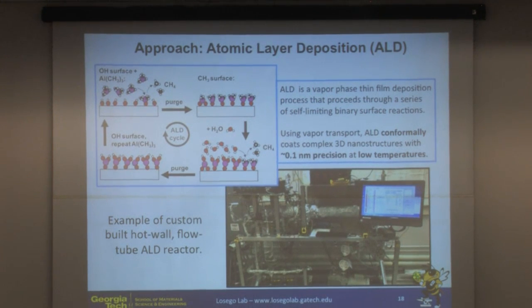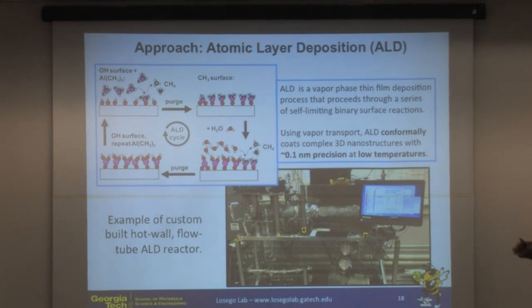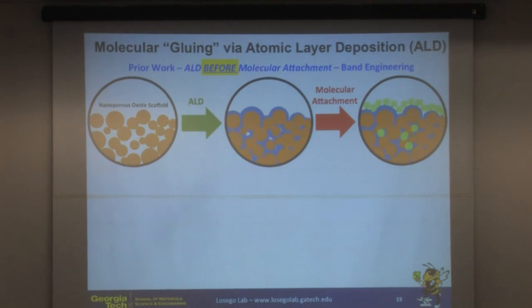Again, I'll remind you that we can conformally coat these nanostructures with no problem. So 10, 20 nanometer particles, we've shown that we can conformally coat those. You saw that on the first slide of this talk. The other important thing here is we can deposit these materials with about 1 angstrom precision. So you'll see in a few minutes that obviously we don't want to hurt the performance of these devices, so we need to be very precise in how much material we're encapsulating these molecules with.